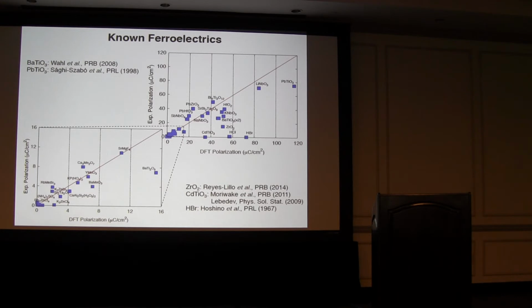For instance, lead titanate, that's a very good example. This value is way overestimated, and the reason for that is because we're using the relaxed DFT structure. If you use the experimental volume, you recover a value that is about 38. Then there's potassium niobate, which was our original prototype, the very first, computed as I showed this morning. And in fact, in our case, the error was less than 10%, maybe 5%. But we used the experimental geometry.